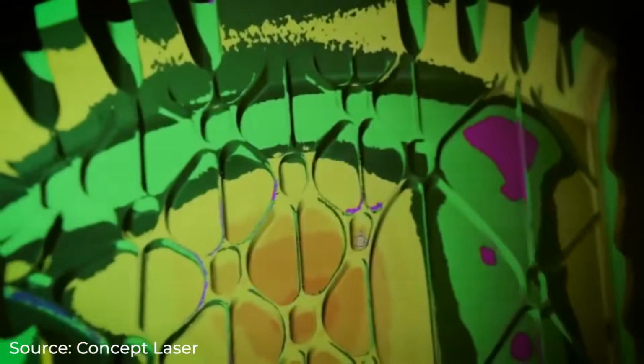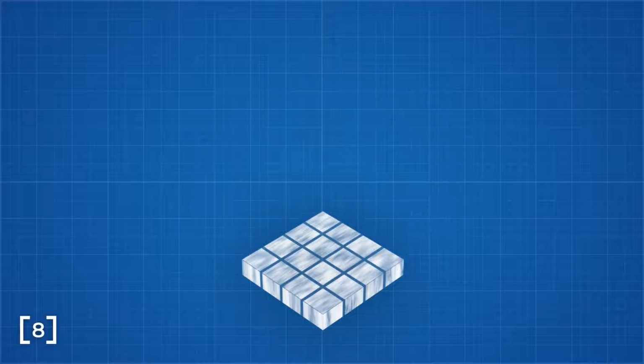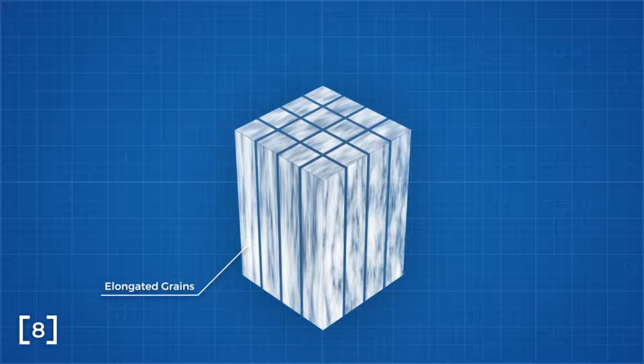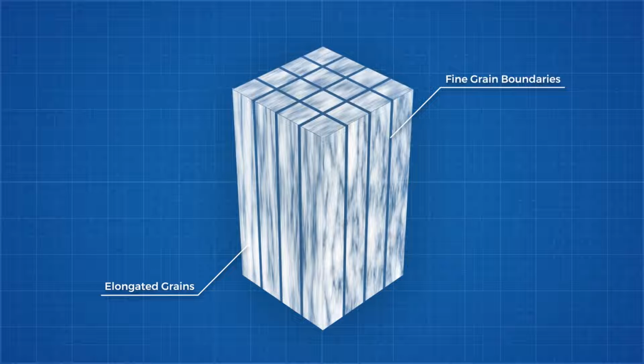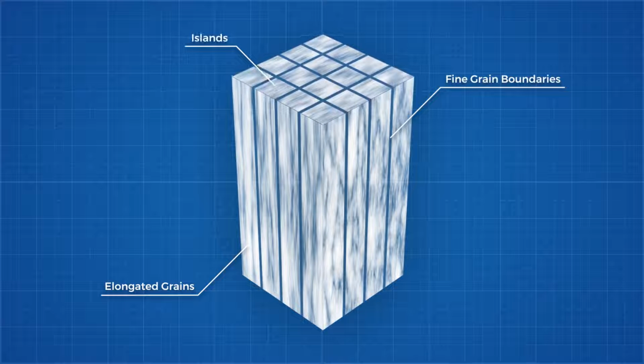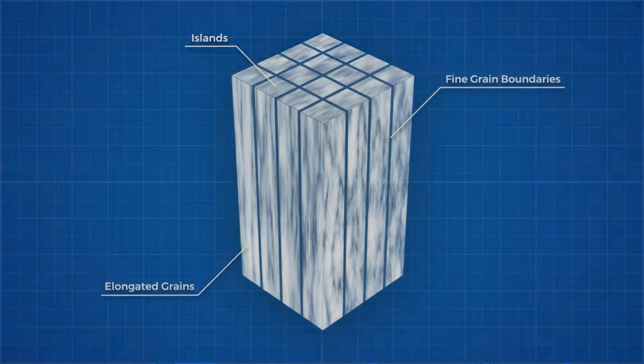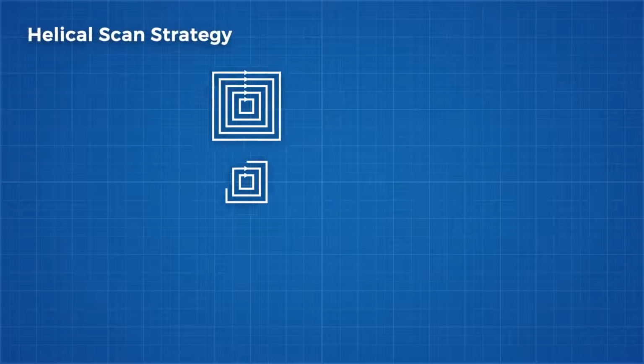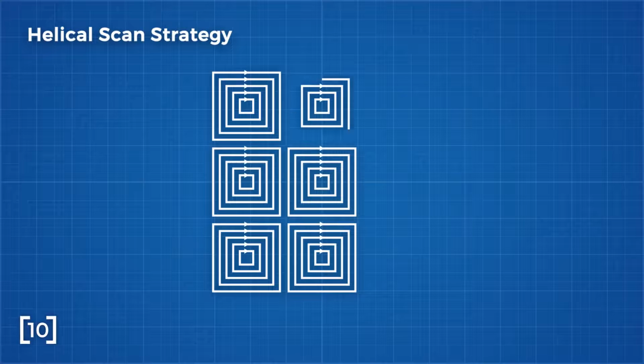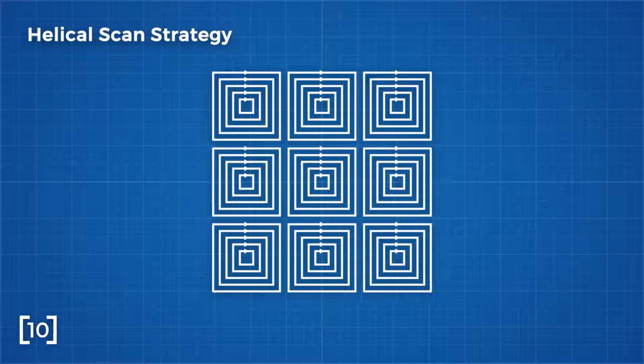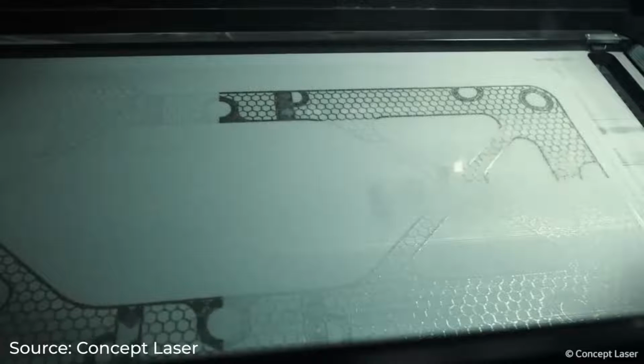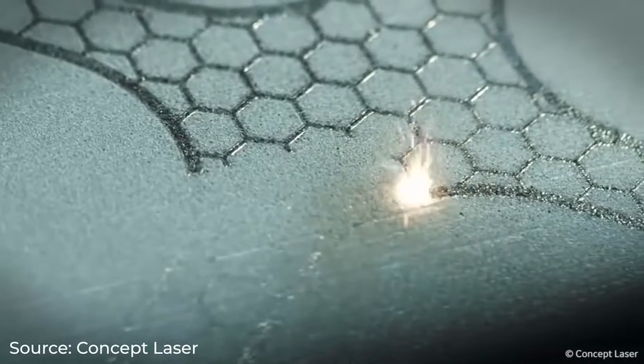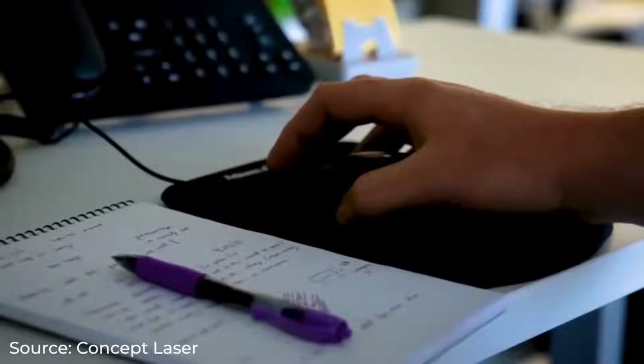However, one study found that this scan strategy has some unique effects on the grain structure, creating those aforementioned vertical grain structures with fine grain boundaries between each island, and these fine grain boundaries had a high density of cracks, which again can grow and cause fatigue failure. There are, of course, alternative laser scan strategies like this helical one. Other researchers are attempting to use thermal and other specialized cameras inside the build chamber to observe the phenomenon like pore formation and inform the laser exactly how to operate with machine learning to maximize material properties.